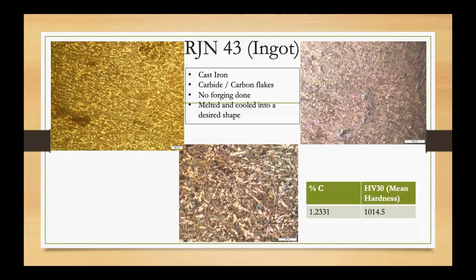So that is very important for us, because we have got the ingot sample from this site. And as you can see, it is basically cast iron, where the carbon content is very high. And here you can see the carbide flakes. The black things are the carbide flakes, and no forging has been done, because the cellular structure has not been flattened.